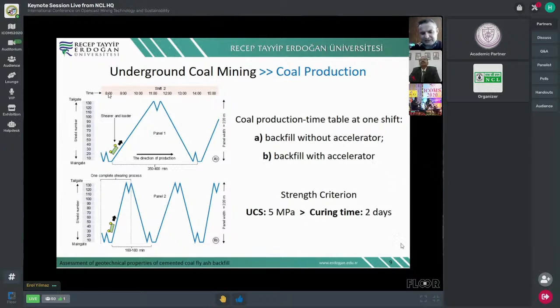As you can see, the strength criterion, UCS, should be 5 megapascal, almost at 2 days of curing time. As you can see here, the backfill with accelerating, you can increase the coal production, but without accelerating, which means backfill not mature, will not allow you to produce a high quantity of coal.